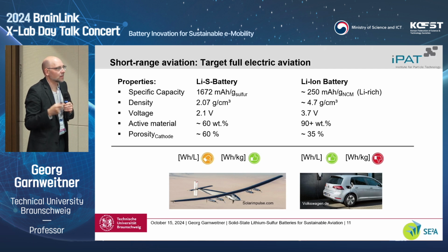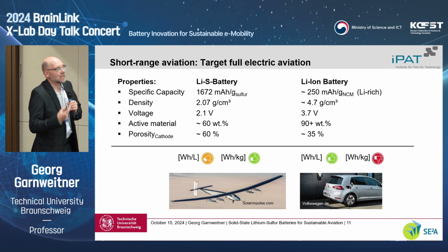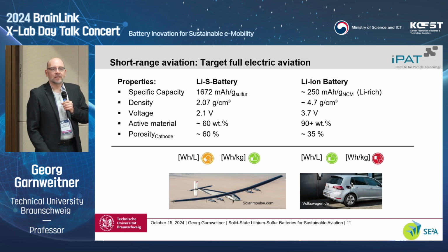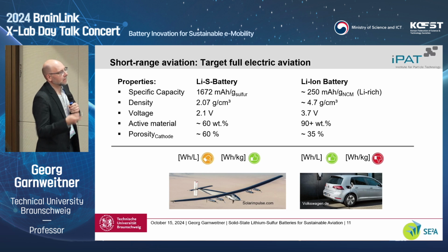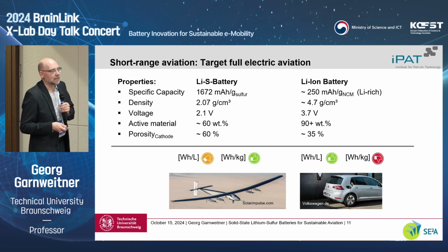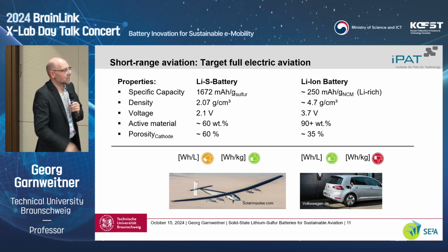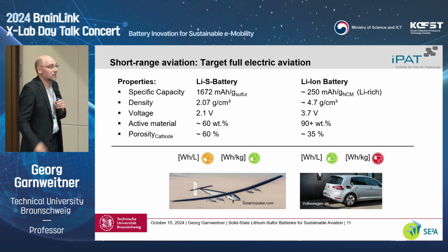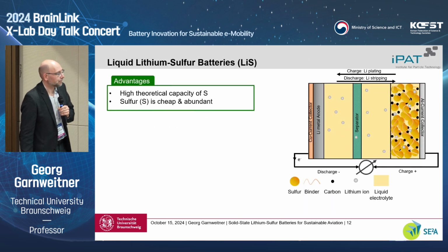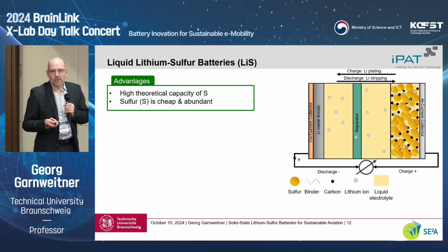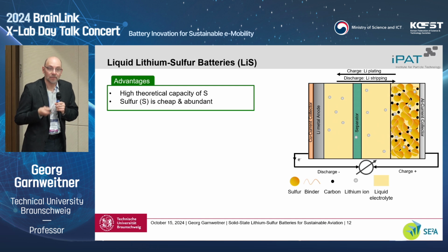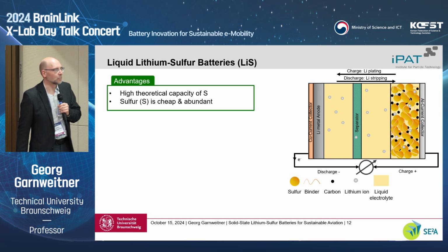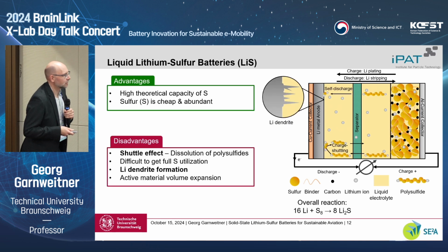The specific capacity is 1,670 milliamp hours per gram of this active material, whereas for a normal cathode material in a lithium-ion battery, we have 250 milliamp hours per gram. So here we are much higher. But we have some, let's say, compromises to make, as you see in the other numbers. And this, nevertheless, makes this lithium-sulfur battery highly attractive. Additionally, sulfur is abundant and cheap, and we basically get rid of these other metal components, these transition metal components, which, of course, for a life cycle assessment also is an attractive factor.